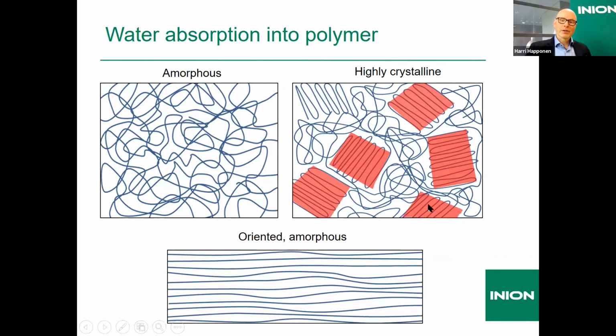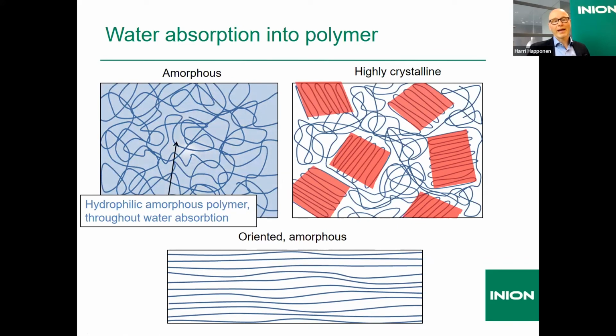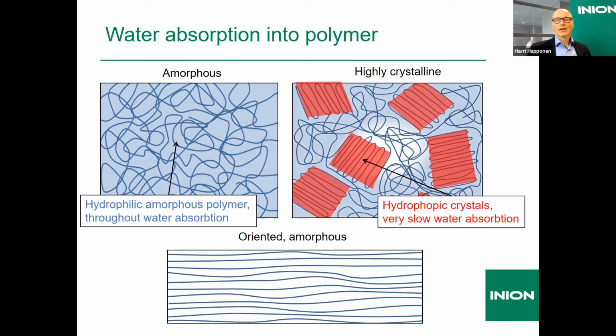But it's good to remember that these early stage polymers were made from highly crystalline polymers, which didn't degrade completely. So nowadays, the implants are mainly made from the amorphous copolymers, and they degrade in a safe way. If you have a highly crystalline polymer, the amorphous sections between the crystals will degrade, but these red areas will stay in the body for 5 to 10 years and may cause some issues during that time.